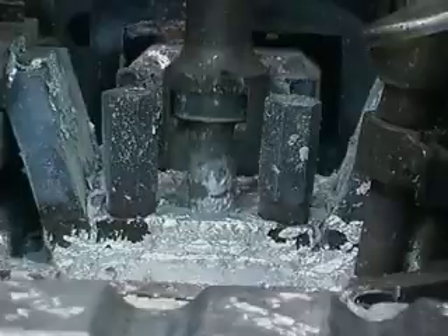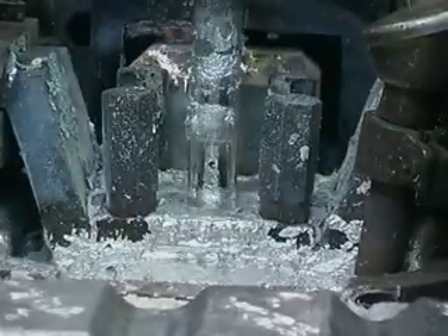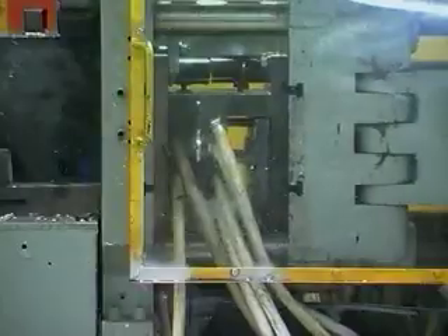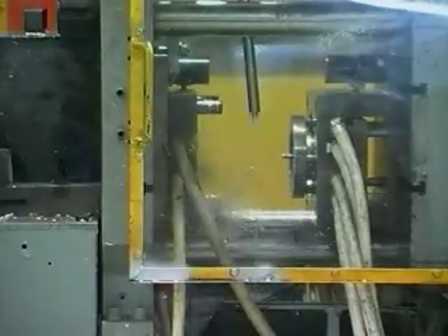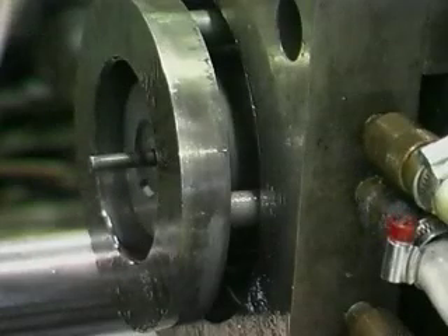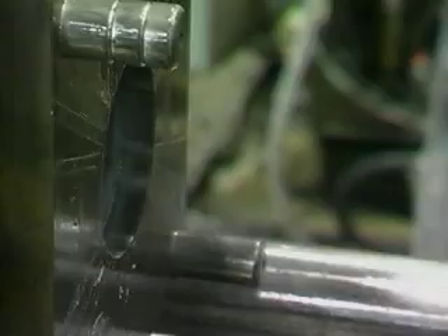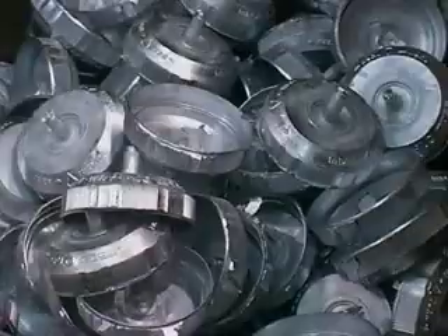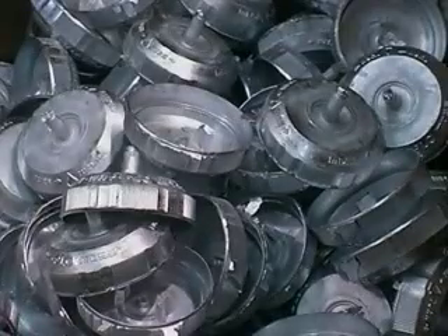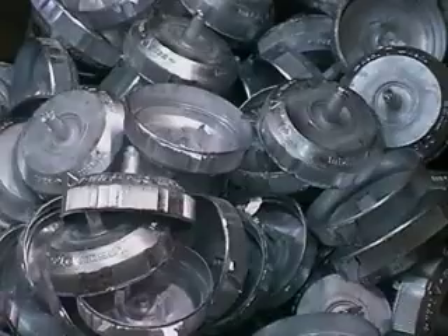As the zinc alloy melts at less than 410 Celsius, the fuel costs are less per unit produced, die life is longer, at least 500,000 units from one die set, and the cycle times are much faster than any other casting process for a similar size component. Hot chamber die casting can produce castings having wall thicknesses as thin as 0.25 of a millimetre and products with very fine surface detail.